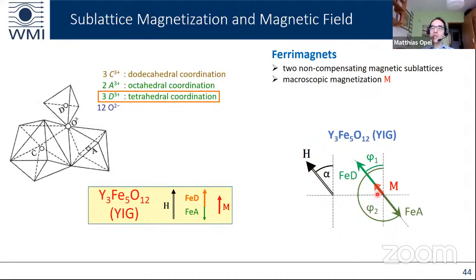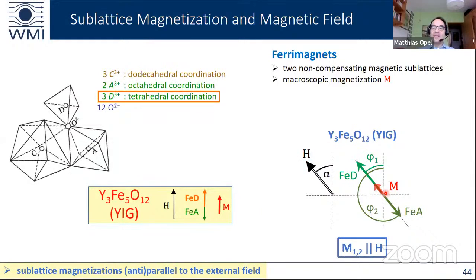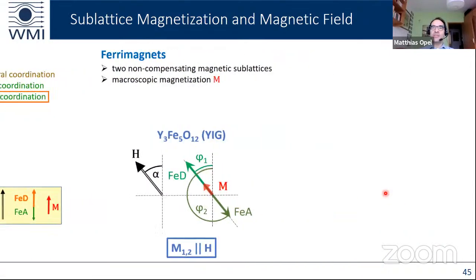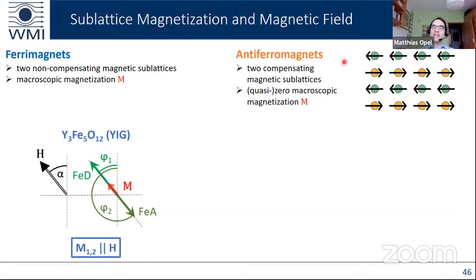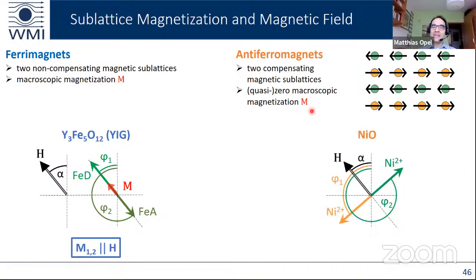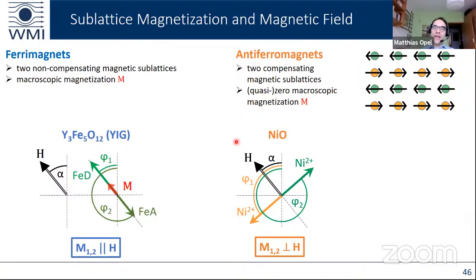And when we rotate H, we can rotate the M, and the angle between H and M is 0 degrees. So M is always parallel to the external magnetic field. This is not the case in antiferromagnets. In antiferromagnets, we have two compensating magnetic sublattices with a quasi-zero magnetization M. And due to energy considerations, these two magnetic sublattices, for instance the nickel 2+ sublattices in nickel oxide, do not orient parallel to an external magnetic field, but perpendicular to it. That means in the antiferromagnets, the magnetic sublattices are perpendicular to the external magnetic field.